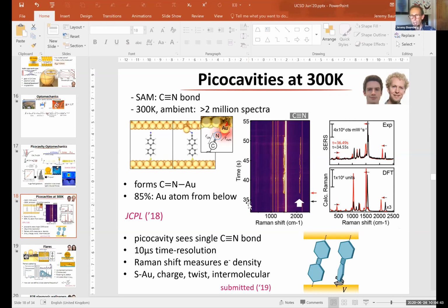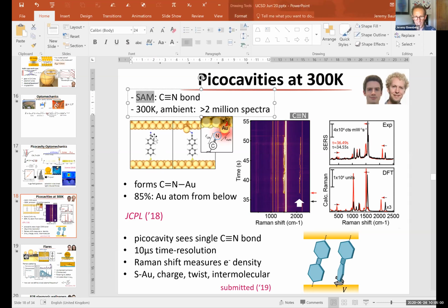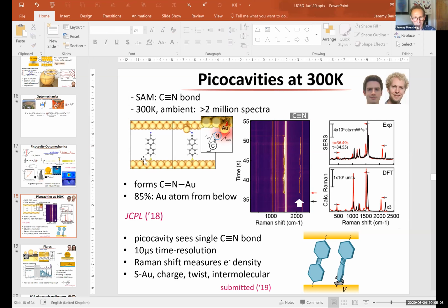That's a really good question. We argue about it a lot in the group, because now we have a way to look incredibly precisely at the molecules. And the more we look into it, the less satisfied we are. Often the STM community has tried to look at the organization of molecules. Here, of course, I'm using a self-assembled monolayer, not a single molecule. So these tend, if I have rings like this, to stack and sit vertically. But they're still tilted. I've drawn it wrong here. They're much more like this, tilted in some direction. The tilt varies with the stacking and the type of molecules.